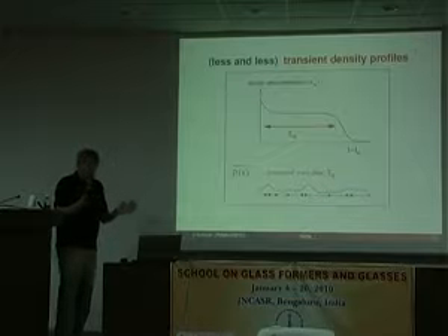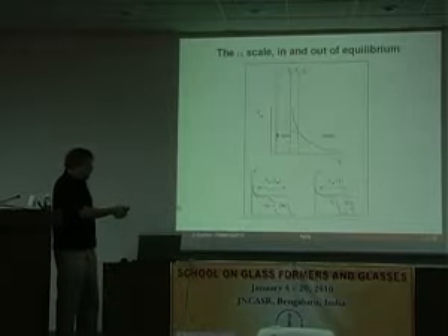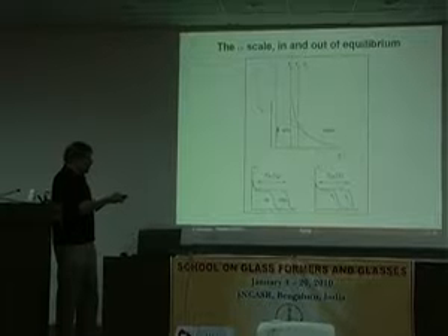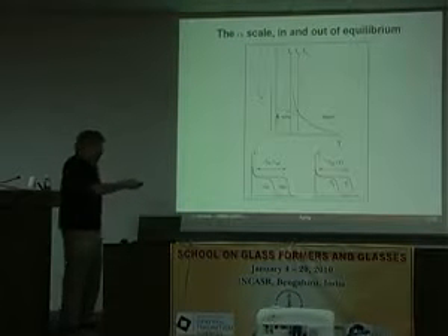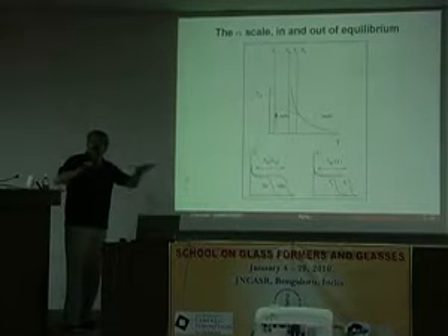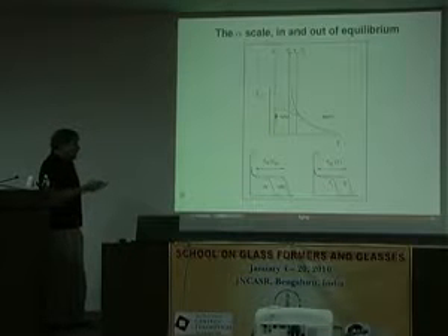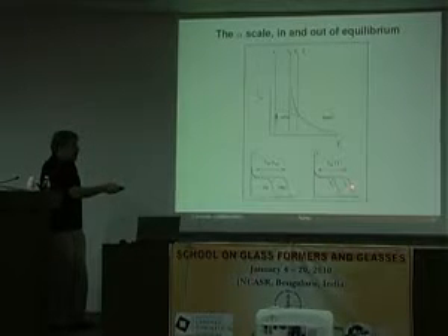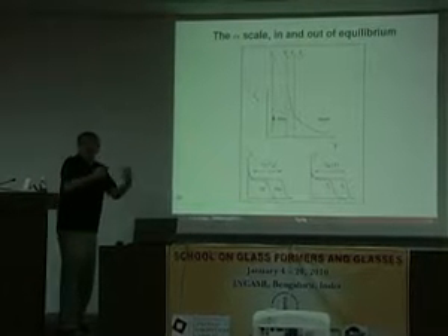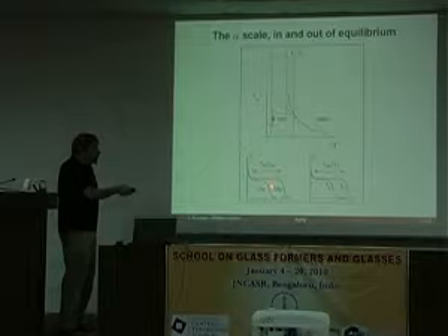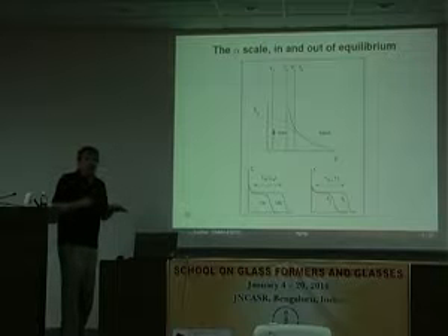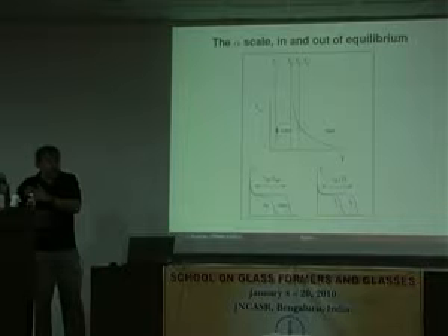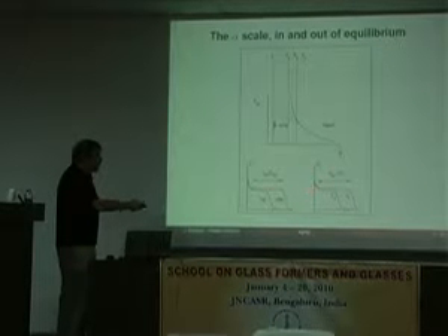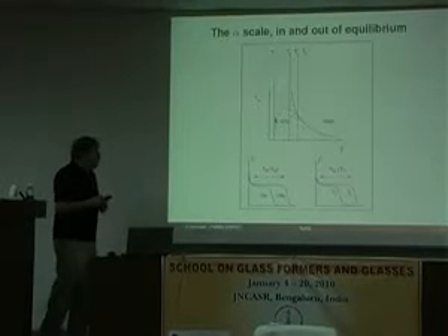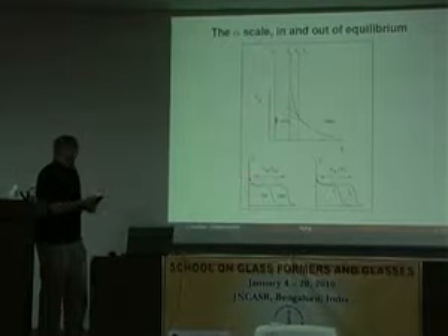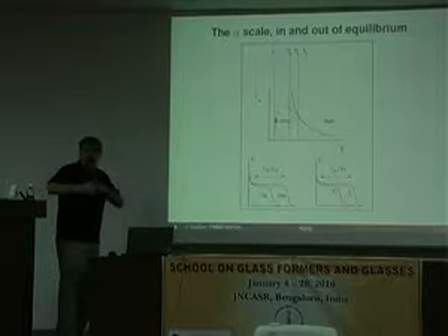You are in perfectly good equilibrium when you are in the true supercooled liquid and in equilibrium. You have these slowly evolving profiles, but the time in which they evolve is long, and it depends on the temperature. So at a lower temperature, this is the typical time it takes for these density modulations to go into something else. On the other hand, if I suddenly quench a system to this temperature, it turns out that this time scale doesn't immediately happen. What happens is that the system slowly accommodates from having a shortish time scale, where rearrangements are relatively fast, more or less of the order of what they were at the previous temperature, and then slowly they work their way to being slower and slower. And this is the aging thing. So aging can be seen here as a tendency to make the average density modulations evolve slower and slower.